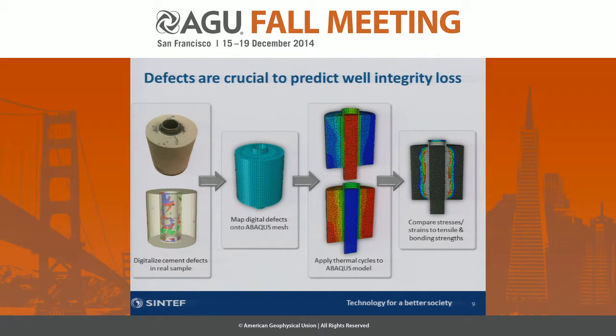So here we saw that with the defects in the cement sheath, you can actually get quite strong stresses in the sample. And this is now ongoing work where we are trying to predict what is going on, and in addition test it in the laboratory. And we are measuring parameters that can be used as input here, for example, the bonding strength, etc.